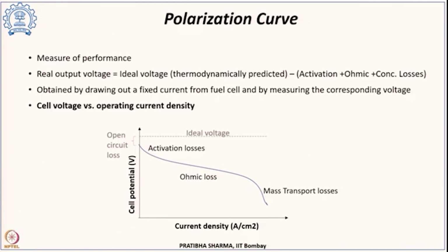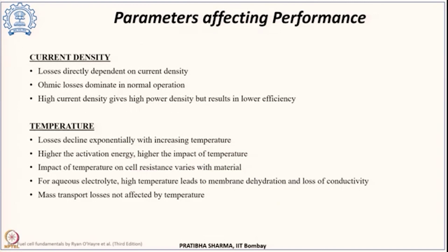So if we consider the performance of a PEM fuel cell, we can plot cell voltage with the current density. The actual output voltage is given by the ideal voltage minus the sum of the different overvoltages. In the lower current density regime, activation losses predominate. In the real operational region, ohmic losses predominate in the medium current densities, and in the higher current density regime, mass transport losses are the predominant losses involved.